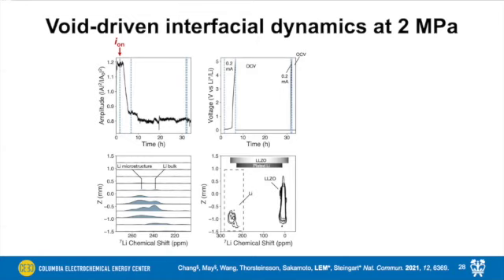And whenever we take this MRI here, what we see is that we have this peak that corresponds to our bulk lithium. So this is from our electrode. And then we have a bunch of lithium microstructures that have gathered at our plating interface. This is exactly what we'd expect because we have these huge spikes in our voltage profile. Basically, we've just plated a bunch of microstructures at low stack pressure.